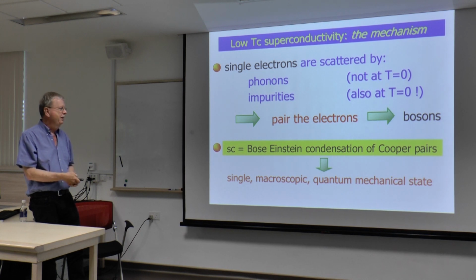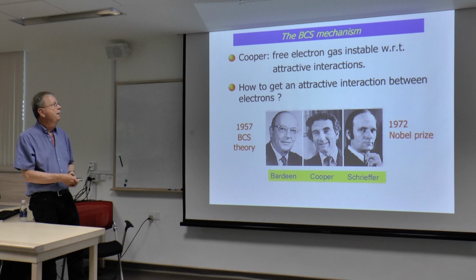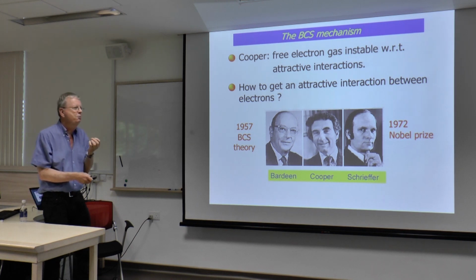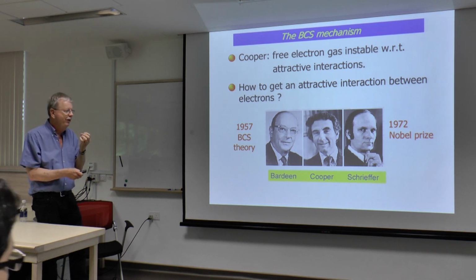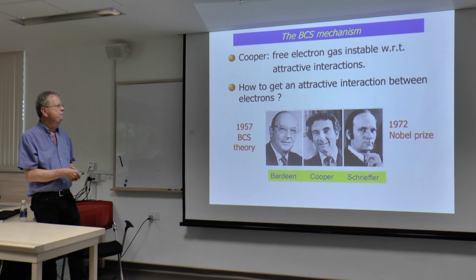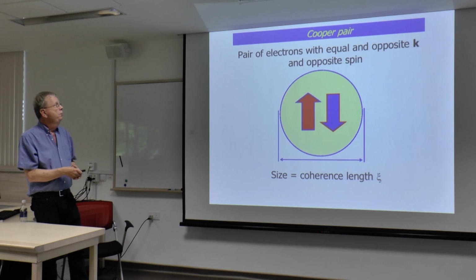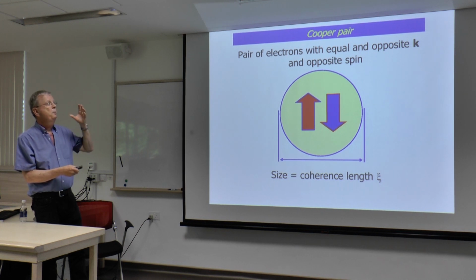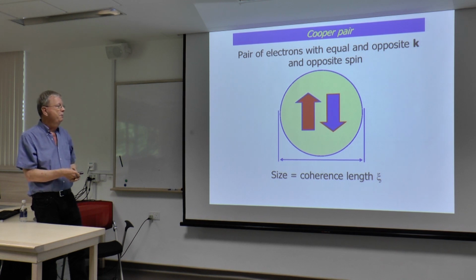So there's a lot of quantum mechanics mixed in here in the superconductivity, which I really will not have time to touch on. But the neat thing that Cooper showed was if there's a slight amount of attraction between the electrons, it's enough to condense into a superconducting ground state. It doesn't matter how small the attractive interaction was, if it's finite, you get condensation. And this is where my upcoming cartoon is going to look wrong, but anyway, if you pair the electrons, they have equal and opposite momenta in K-space. I'm talking real space, I'm talking K-space, and they have the opposite spin, so they're a spin 0 boson. And the size of this pair, as we discussed, is something like the coherence length.